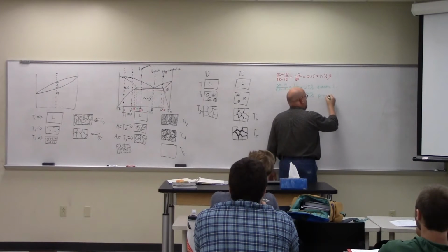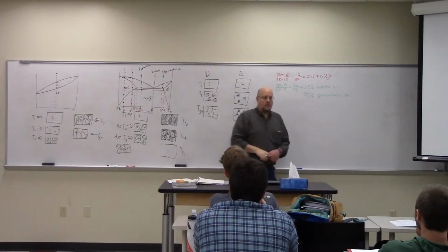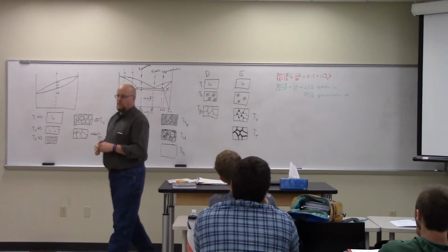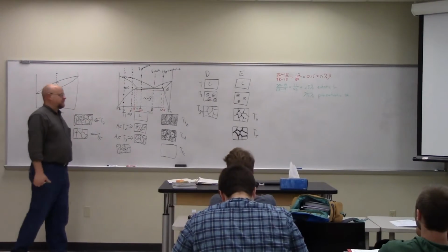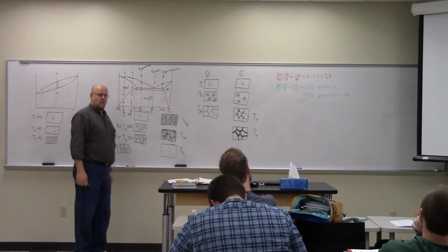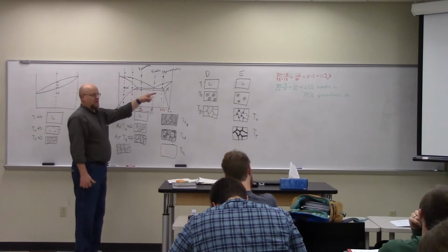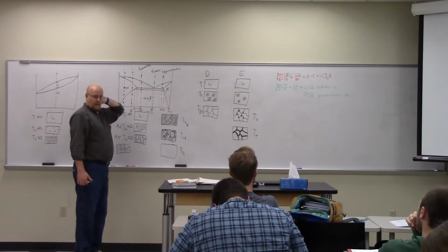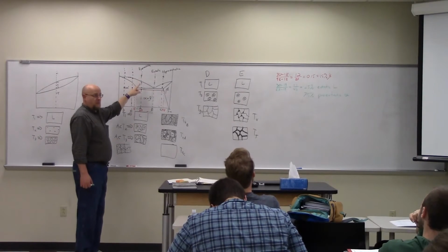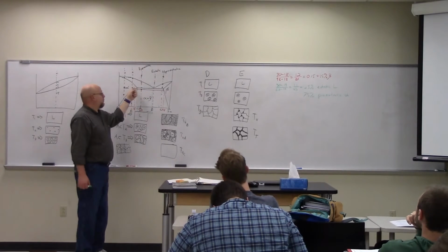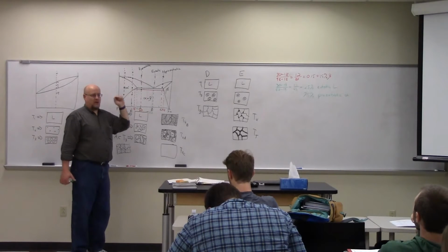is pro-eutectic alpha, before eutectic. So it is alpha that is formed before we went through the eutectic. Everybody see that? We're talking about just above the eutectic. The green, just above the eutectic. So the green stuff, right before I went through the eutectic transition, I had 75% pro-eutectic alpha, I formed all these little alpha crystals. And then 25% was eutectic liquid.